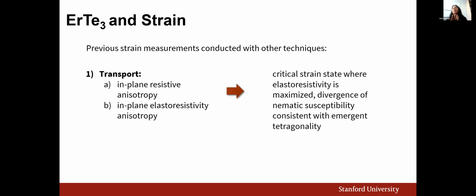All right. We've also been able to study this material under strain with different transport measurements, specifically looking at the anisotropy in the in-plane resistivity and the in-plane elastoresistivity. Particularly, these measurements have shown us that there is some intermediate strain state where the elastoresistivity response of our sample is maximized, which at this point would correspond to a divergence in our nematic susceptibility, which is consistent with what we'd expect to see with an emergence of a fourfold symmetric state in our system, or at least a fourfold electronically symmetric state.